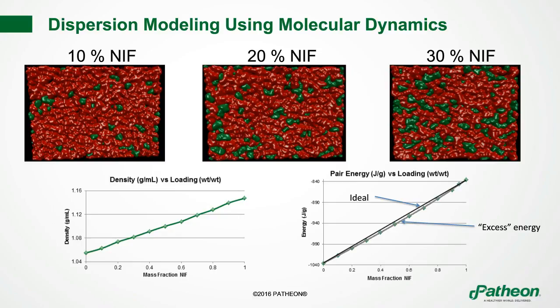The polymer and the drug might not have very good complementarity. So the drug might actually have electrostatic surfaces that are oppositional to the electrostatic surfaces of the polymer, and in that case you might see agglomeration of drug. Or you might have very intimate mixing of the drug and polymer because they are very complementary in terms of their surfaces and shapes. Now, if you look at the 30%, you start to see even more.